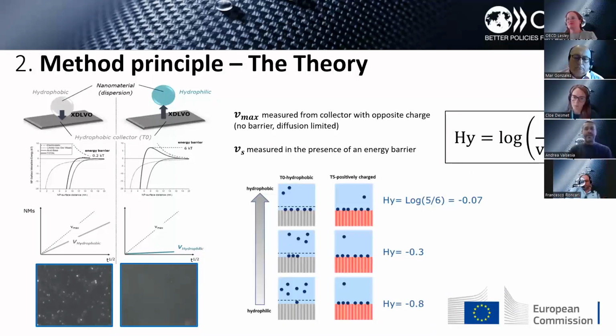So how do we define the hydrophobicity index? The hydrophobicity index is the log of the velocity of binding of the particles on the hydrophobic collector, normalized to the maximum velocity of the particles on the collector without an energy barrier. This means we are measuring a ratio of particles that prefer to stay on the hydrophobic collector instead of staying in the water dispersion.